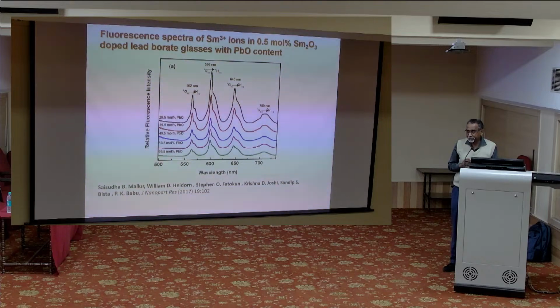The extent to which they overlap, and the technical term that we use is crystal field, the electric field produced by surrounding charges and surrounding electron cloud, they all vary as a function of the glass composition. That variation will be reflected in the light which is emitted by the samarium ion. Excellent question, Dr. Kamla. So that variation is what we are seeing as a function of the glass composition. You can see that there is a slight shift in the peak position of each peak, and there will be variation in the width of the peak. Technically we use what is called full width at half maximum. If you have any Gaussian profile, that is a quantitative measure of the variation in that Gaussian profile.